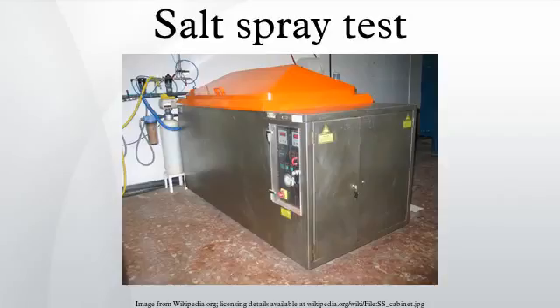The second climate cycle comprises 0.5 hours of continuous indirect spray of neutral saltwater synthetic seawater solution, which falls out onto the specimens at a rate of 1.0 to 2.0 ml/80 cm²/hour. This is followed by 0.5 hours of dosing with SO2 gas at a rate of 35 cm³ of chamber volume, followed by 2.0 hours of high humidity soak.